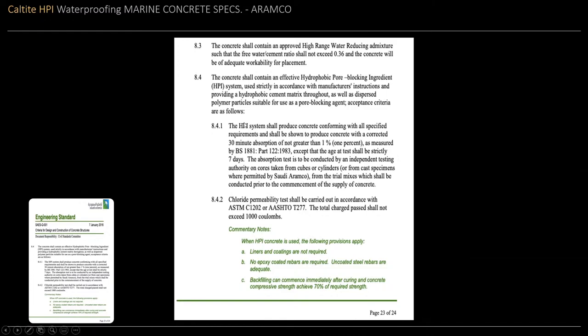And they again refer to HPI system concrete. Again, it's mentioning that it's a performance specification. They're not mentioning any product by name, but 30-minute absorption not greater than 1% measured by BS 1881 Part 122 at 7 days. And also they stipulate a chloride permeability test, total charge pass through not exceed 1,000 coulomb.